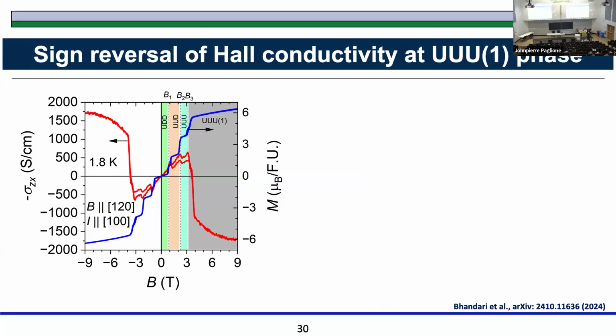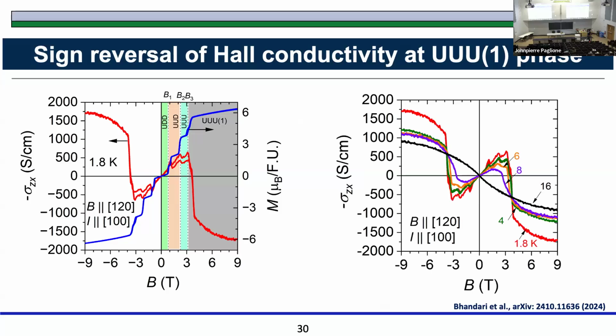What we realized is that for that you need to look into the temperature dependence of this. So above the magnetic ordering temperature, this black curve is all negative. So it shows n-type behavior. The electrons are the majority carriers. Okay. When the antiferromagnetic ordering happens, the magnetic structure becomes large. It's a 3 by 3 or root 3 by root 3. And because of this large spin structure, the electron band folding happens. Because of the band folding, you have more hole pockets than electron pockets in the Fermi surface. So that makes your conductivity positive here. It's negative above, right? So this is a hole-like behavior.